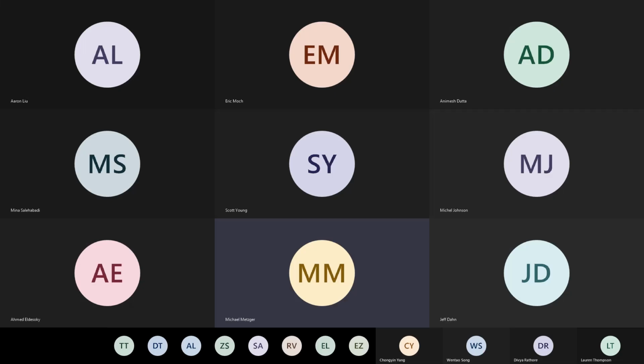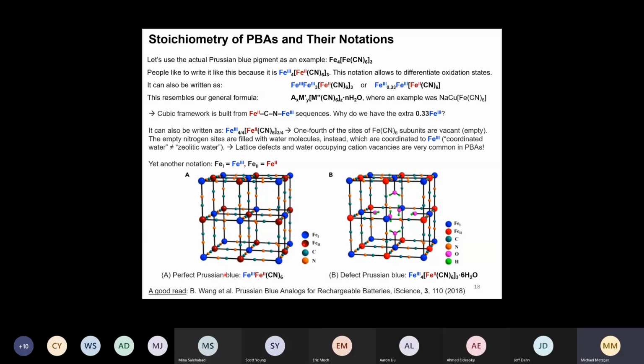Geometry doesn't perfectly add up as it would in the perfect Prussian blue. Plus, we have 6 of these coordinated water molecules. And this is really covalently bound water molecules to these atoms in the structure. It's not the zeolitic water or interstitial water that would sit in these open framework sites that we discussed before. So both these things are possible in this material.